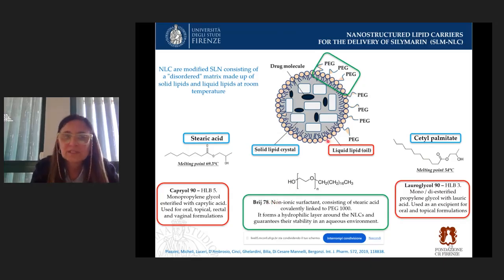This surfactant is characterized by the presence of a PEG moiety that prolongs the circulation time of the carrier. Another, the second NLC I formulated to improve the characteristics of Silymarin extract, contains cetyl palmitate as a solid lipid, Lauroglycol 90 for liquid lipid, and Brij 78 as a surfactant.